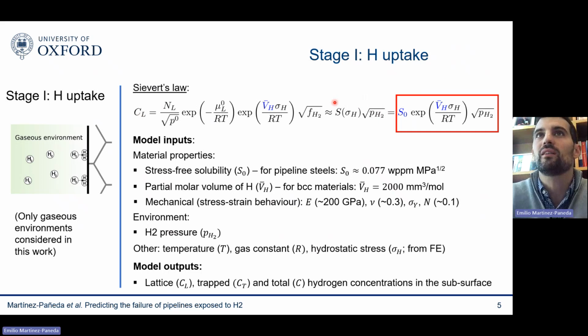And what is here is the solubility of the material, which is a material property that we can measure. And the only thing to take into consideration is that this solubility is dependent on the hydrostatic stress. So you need some sort of finite element model to calculate the hydrostatic stress if you're interested in knowing what the hydrogen uptake ahead of a defect is.